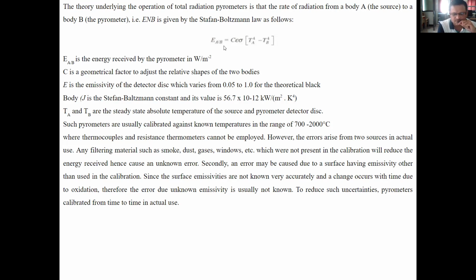However, errors arise from two sources in actual use. Any filtering material such as smoke, dust, gases, windows, etc., which were not present in the calibration, will reduce the energy received, hence cause an unknown error. Secondly, an error may be caused due to a surface having emissivity other than that used in the calibration. Since the surface emissivities are not known very accurately and change with time due to oxidation, the error due to unknown emissivity is usually not known. To reduce such uncertainties, pyrometers are calibrated from time to time in actual use.